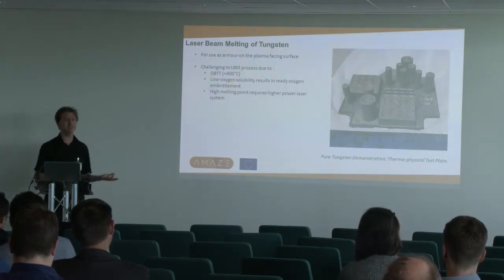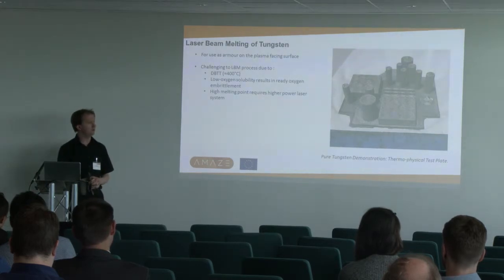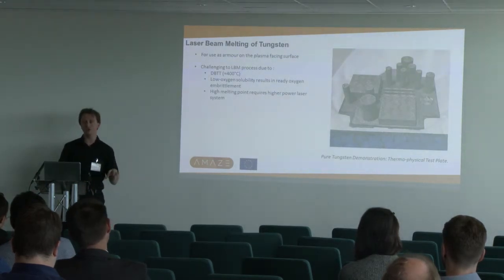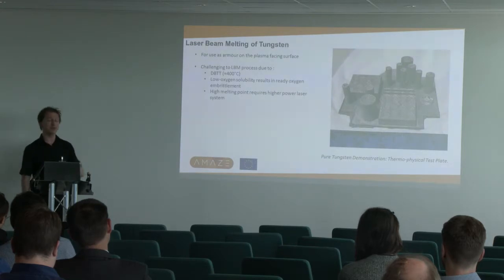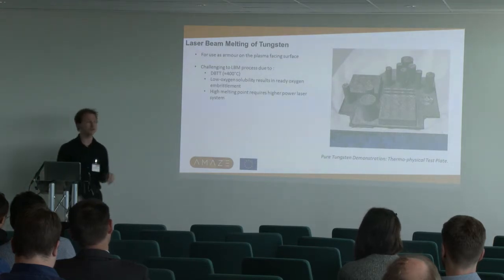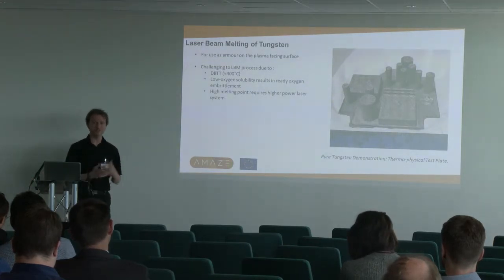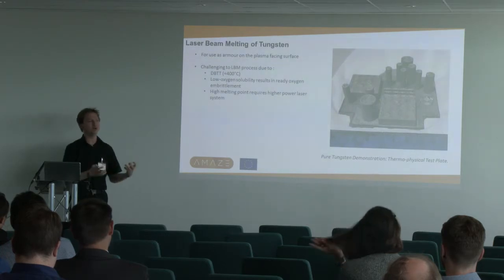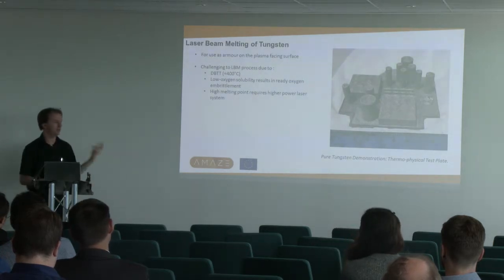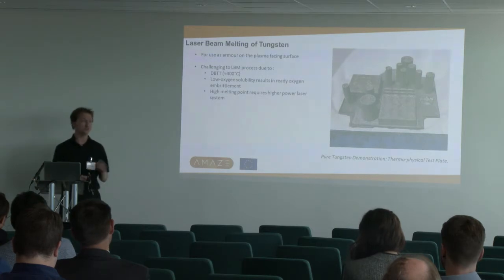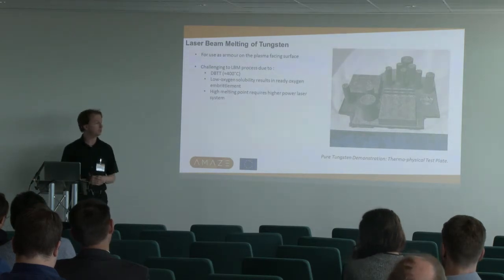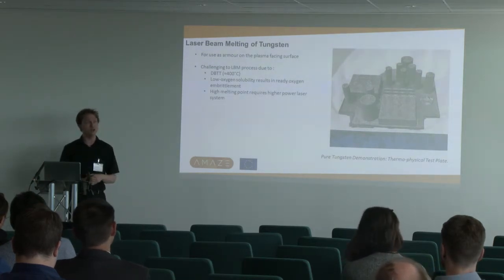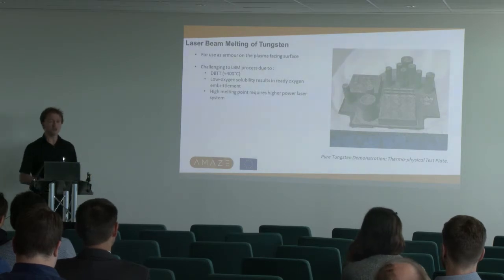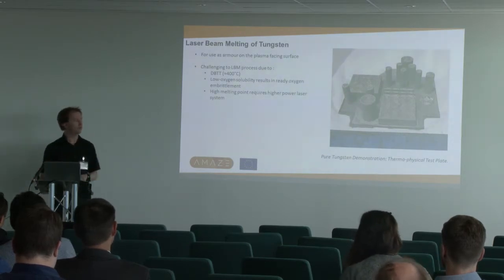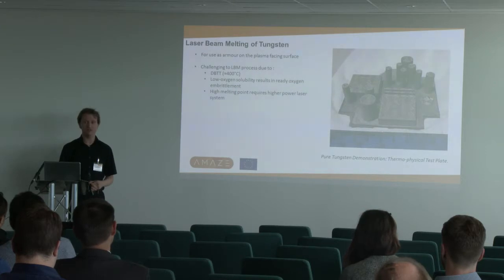And of course, it's a high melting point material, and a lot of the early papers that were published on tungsten used tungsten powder with a low melting point binder material, so they were not melting the tungsten, they were just melting the binder and creating a dense part through that. With our 400 watt system, we're actually melting the tungsten, so this is pure tungsten that's being melted and consolidated. It's only in recent years that those high power machines have become common enough that we can start to look at this as a viable option for making shapes in this material.